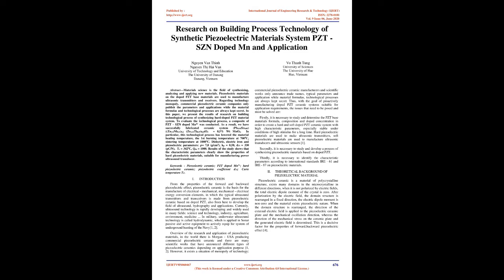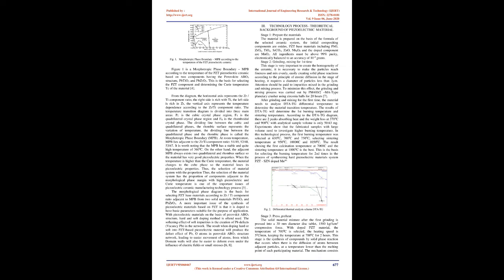Theoretical Background of Piezoelectric Material: Piezoelectric ceramic is a material of polycrystalline structure. There exist many domains in the microcrystalline in different directions. When it is not polarized by electric fields, the total electric dipole moment of the crystal is zero. After polarization by the electric field, the domain structure is rearranged in a fixed direction, the electric dipole moment is non-zero and the material exists piezoelectric nature. When the domain structure is rearranged, the direction of the external electric field is applied to the piezoelectric ceramic plate and the mechanical oscillation direction, whereas the direction of the mechanical stress on the ceramic plate and the generated electric field is determined. This is a decisive factor for the properties of forward-backward piezoelectric effect.